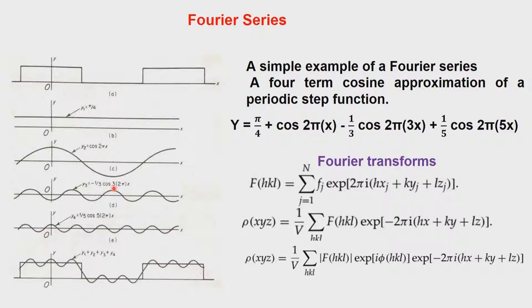What has happened here is that we have a function chosen in such a way that it mimics the actual electron density distribution inside the crystal. To mimic that, we express it in terms of the Fourier series, which we have discussed using a four-term expression. We see it is almost there — adding four more terms makes it better and better. So ρ(x,y,z), as we keep adding over all possible HKLs, gives the best possible identification of the electron density. That is the logic with which we build up the Fourier series.